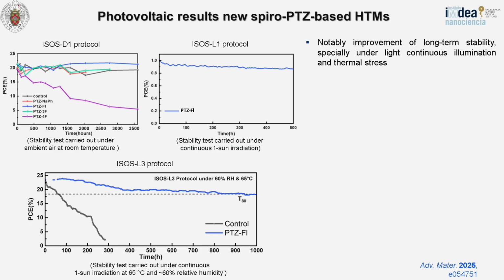And you can see here that in all of them, with the only exception of the fluorinated one, they exhibit a very long-term stability under continuous light illumination and thermal stress. So this is really fantastic, one of the best in terms of those compounds reported. And they have been subjected to the ISOS protocols. This is for durability and also under light illumination. And this is under stress.